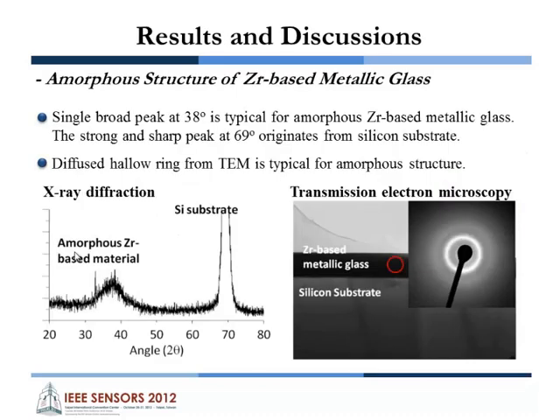The excellent property of the metallic glass is due to its amorphous structure, so it is very important to confirm the amorphous structure of the metallic glass after fabrication. We have two methods to confirm the amorphous structure. The first one is X-ray diffraction. This picture shows the X-ray diffraction results, and we can see the broad peak here is the typical Zr-based metallic glass peak, and this sharp peak originates from the silicon substrate. The second method is the transmission electron microscope, and we can see the diffuse halo ring here is a typical amorphous structure image. So from both results, we know the fabricated metallic glass thin film has an amorphous structure.